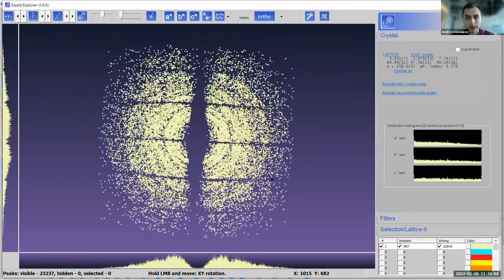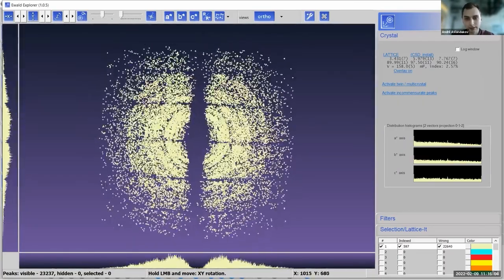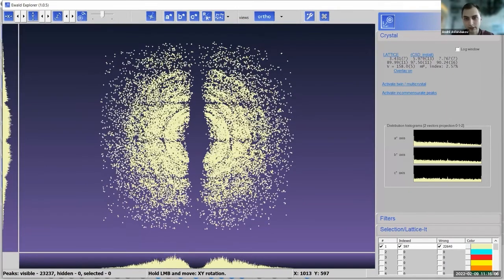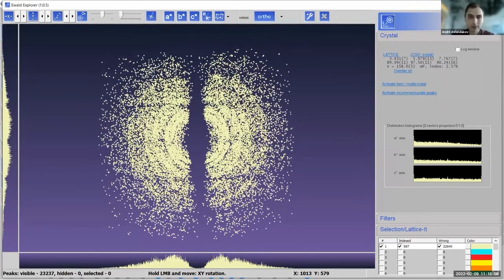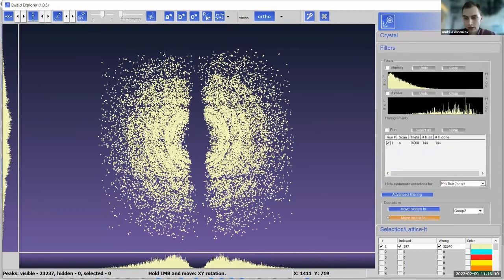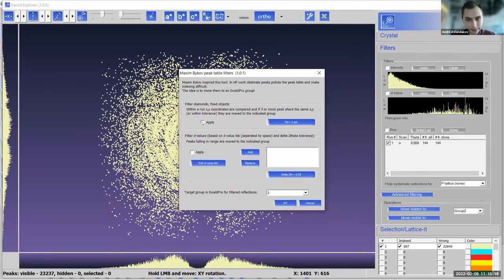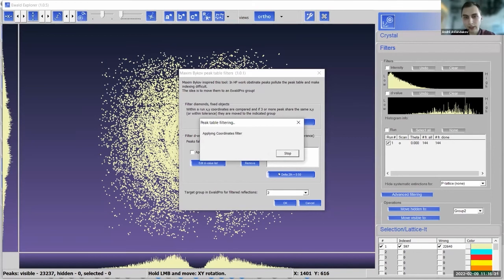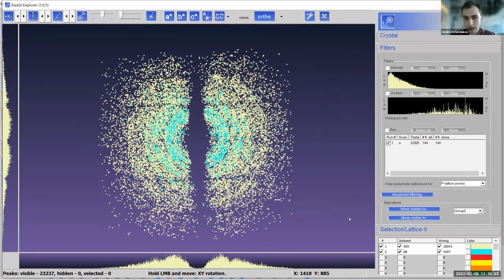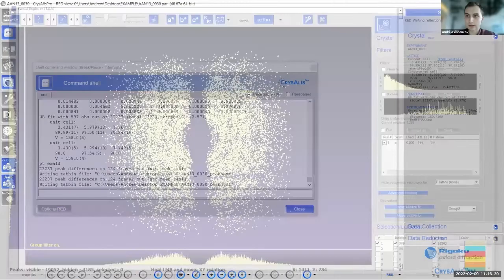And of course, by eye, it's very difficult to find reflections belonging to the distinct single crystal domain. So as long as this data is from a diamond anvil cell, firstly, we can apply advanced filtering to remove diamond reflections. And after that, we have 19,000 reflections. Then we can close this.